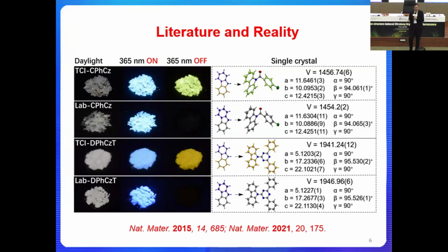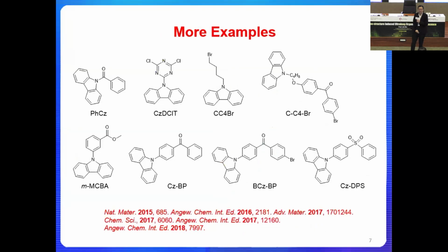And we tried other examples. Again, if we use commercial molecules as the starting materials, we are able to reproduce the phenomenon in the literature. But if we use pure compound to start with, we will not be able to reproduce that signal. All right, and then we did detailed analysis of the single crystal structure and everything. With the impurity and without the impurity, there's no difference in the crystal structure, because the amount of impurity is extremely small in this case.